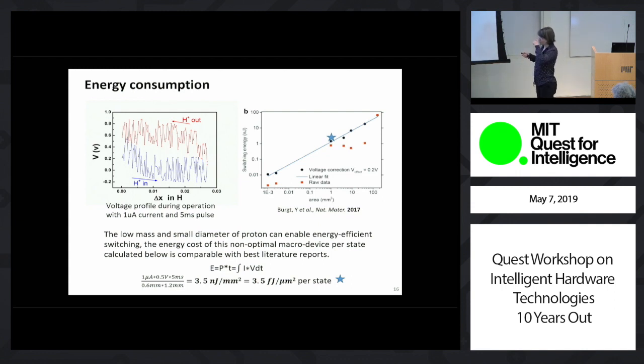But nevertheless, from the voltage change during current pulsing, we can compute the energy consumption per state, and that comes to about 3.5 femtojoule per square micrometer per state. And if we compare that to the state of the art in literature, which was the organic proton device that I referred to earlier, it's comparable to that.